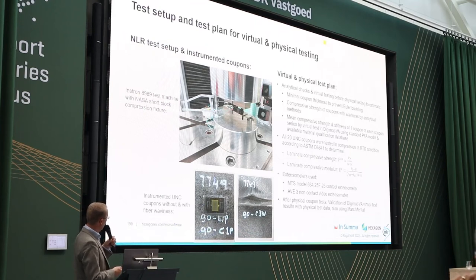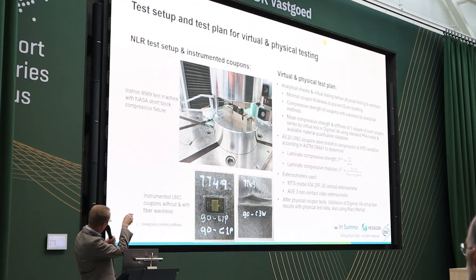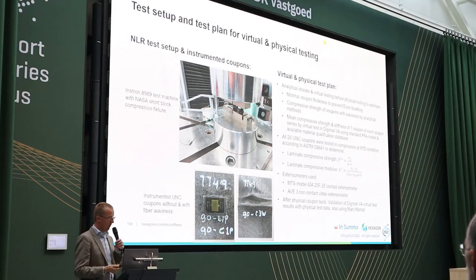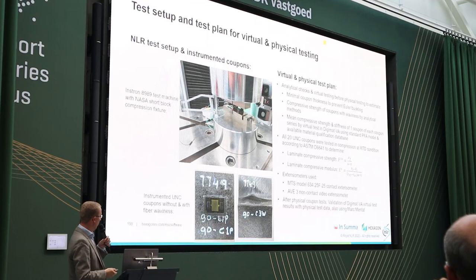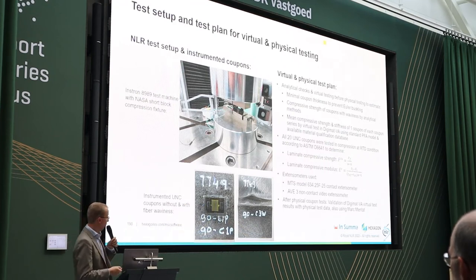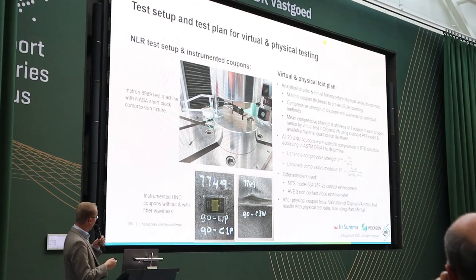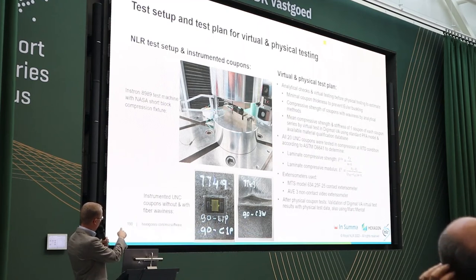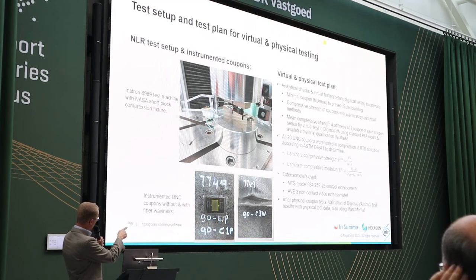Performed with all these 20 coupons, I determined the compressive strength and also the compressive modulus. I used the extensometer to measure the compression displacement, and I also used the non-contacting video extensometer, with two cameras at the back, to capture the failure mode and also measure the strains on the side. After the physical testing, I did some validation to compare the Digimat virtual test results with physical test data. For this, I not only used Digimat as a post-processor, but also Marc Mentat to extract, for example, the strain at the strain gauge locations. I instrumented the coupons, as you see in the bottom left: without waviness, I had back-to-back strain gauges, and with waviness, I had one strain gauge on the flat side.